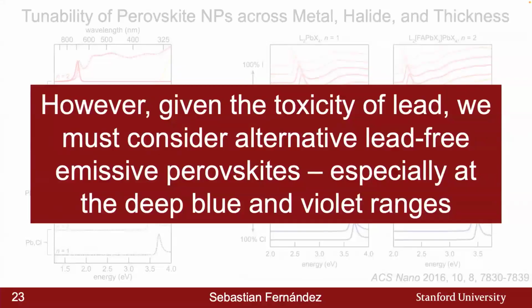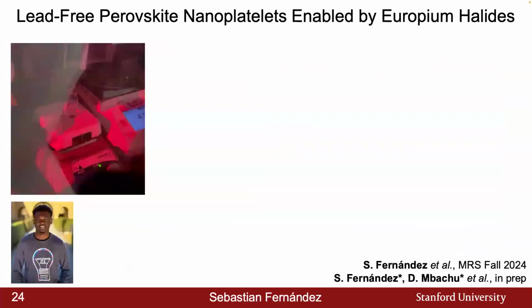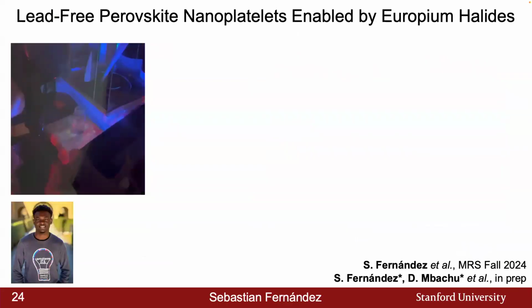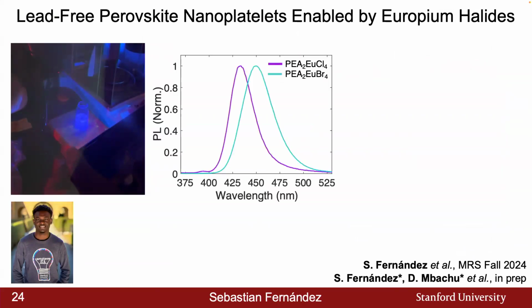And if we're really going to think about how we can integrate these technologies further, we need to consider alternative lead-free technologies. And so here, in conjunction with D. Mbachu, who's within the group, we can play the same trick. We can have our crystallization solvent, which is stirring, and drop our europium-based halides, so purely lead-free, to create these deep blue and violet light-emitting perovskite nanoplatelets. In this case, the ligand species is phenethylammonium, which is annotated here. And in general, we can see that the pure bromide-based materials will emit at the deep blue of around 450 nanometers, while the pure chloride-based system will emit at around 430 nanometers, which is now in the violet regime.